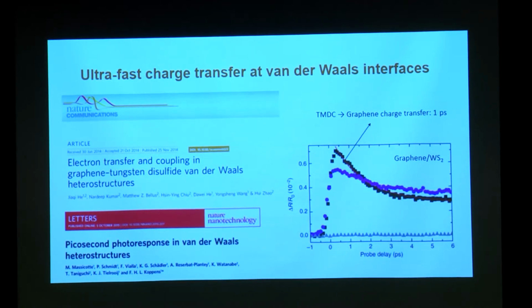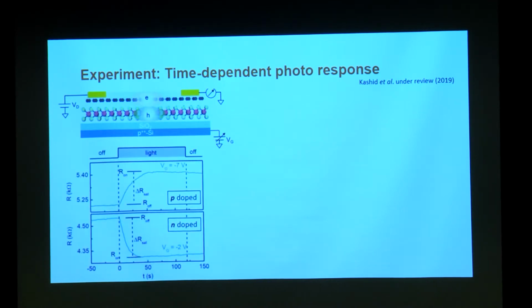That's fine, that's great. So in which case, one should ask the question: if the electron goes within 1 picosecond, and it takes about a nanosecond to cross the graphene, then if I look at the current, from the light on, the current formation should not take more than a nanosecond. The answer to that question turned out to be particularly surprising.